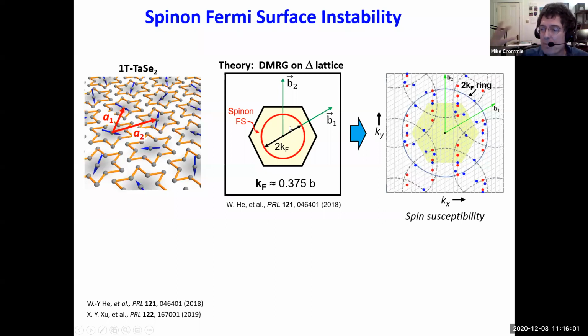Now, that is not surprising because whenever you have a Fermi surface, you always get peaks in the susceptibility at 2kF. That's like a famous solid state physics thing. But what was strange is that there were certain wave vectors where they were unable to see a peak. So at these very special wave vectors, there was no peak in the susceptibility in the gamma-M direction. And so one hypothesis for why that's happening is that the spinon Fermi surface is gapped in these particular directions. So it should look like this. You see how I gapped it.